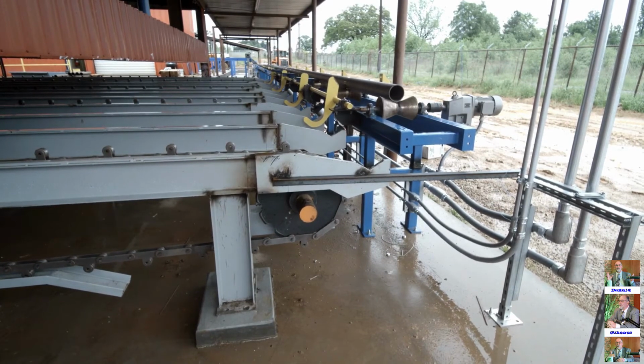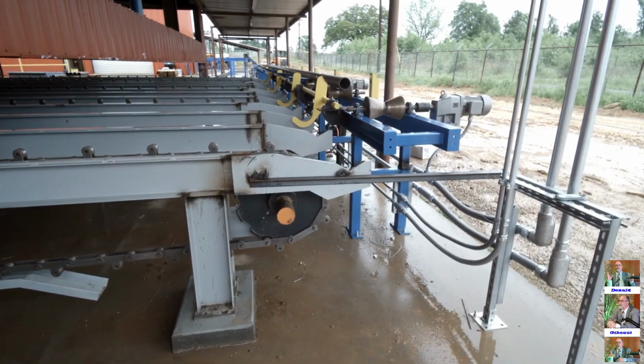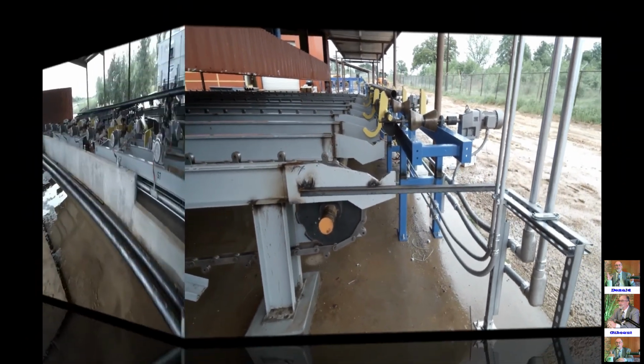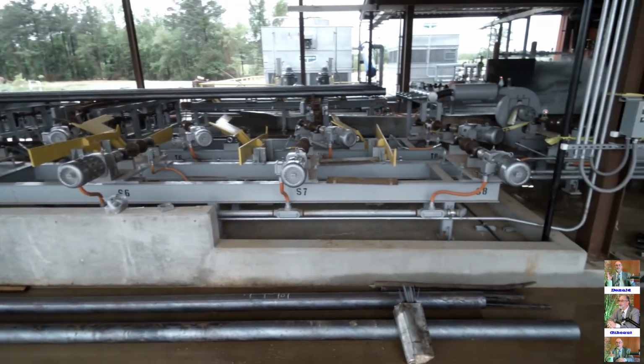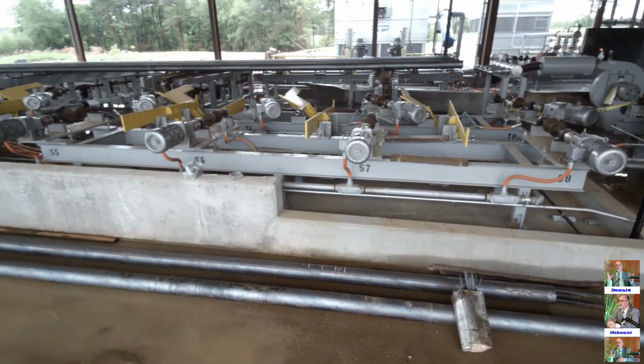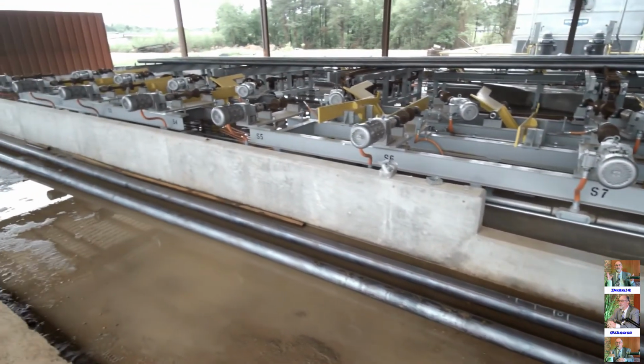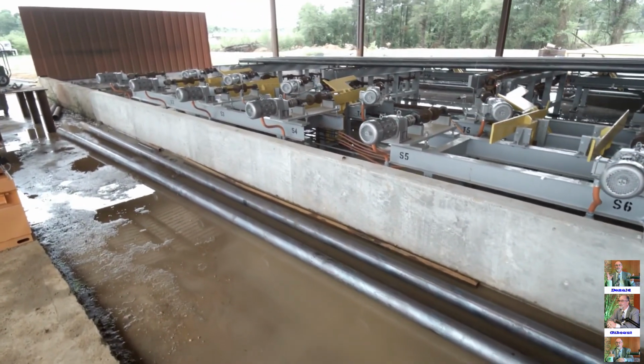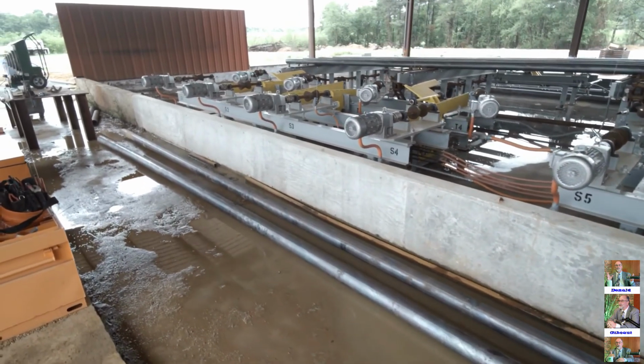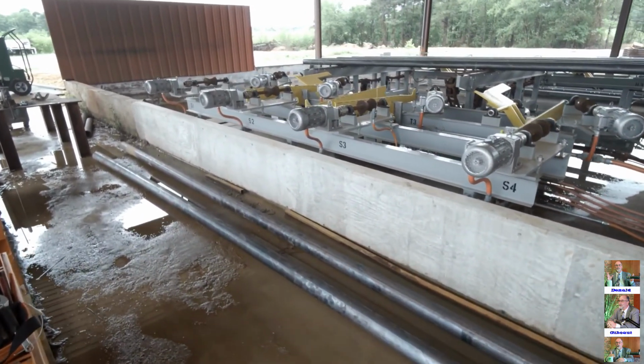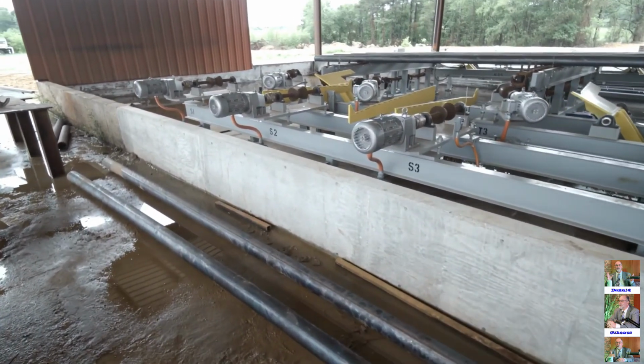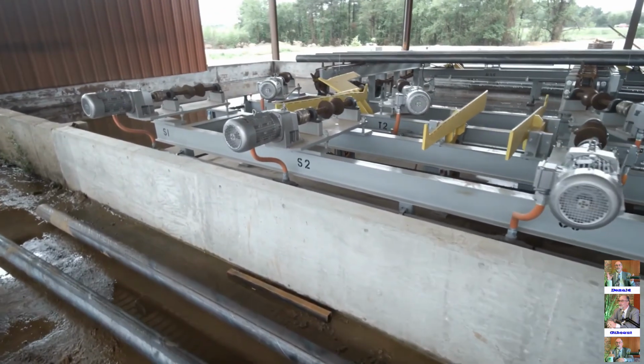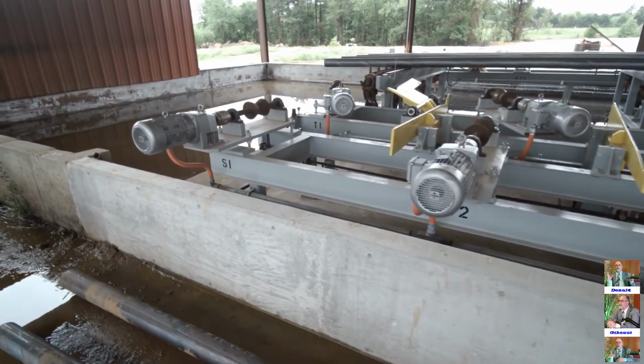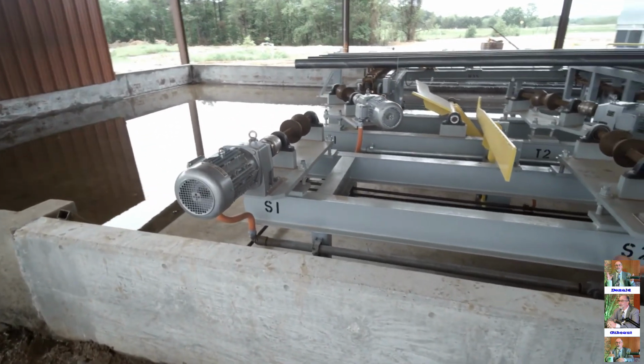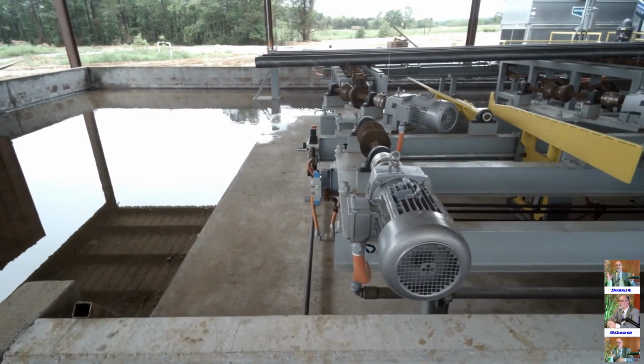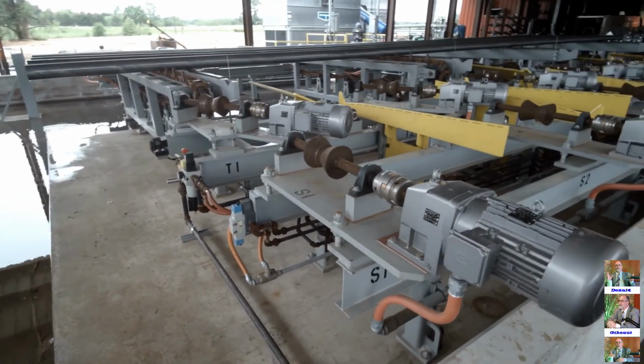It then takes it over and it gets coated in line, and then it has a hydro tester and a stenciling machine on the other end in that other building there behind. So now we're over to the transfer table of the U-shaped line, and here is the position for the as-quench sample position. That set of paddles will lift a pipe off of this before it goes into the temper, and then it's fed to a stop on the front end there where a plasma cutter will cut off a sample. Then it's reversed, and then a gap is built on this transfer table to put that cut sample pipe length back in the line so that it can run through the temper and be counted as a good pipe at the end of the day.